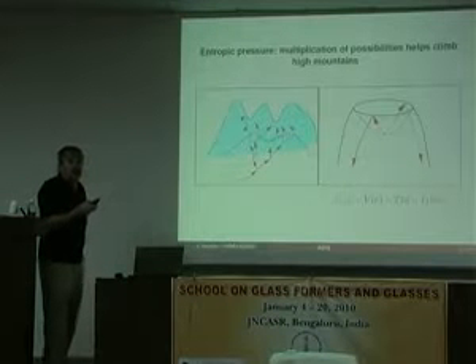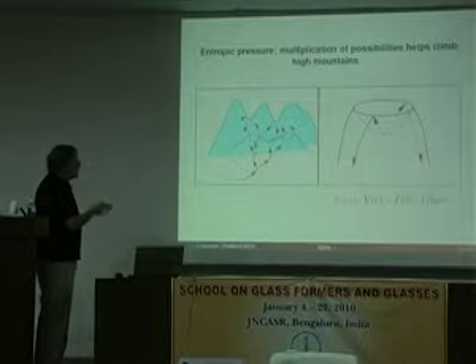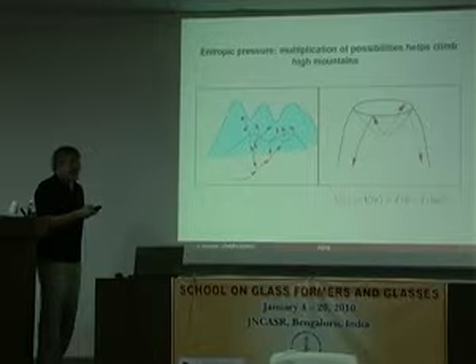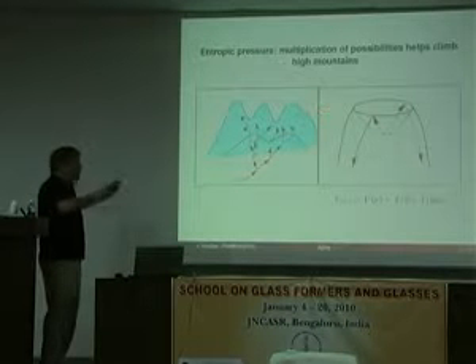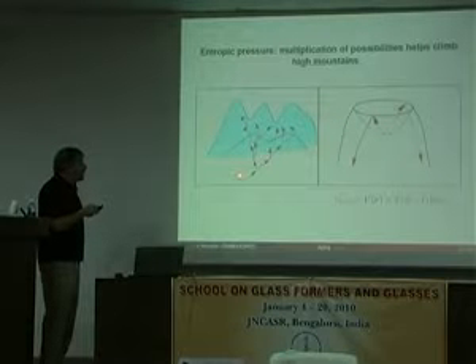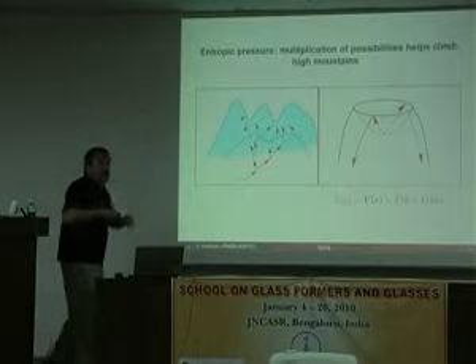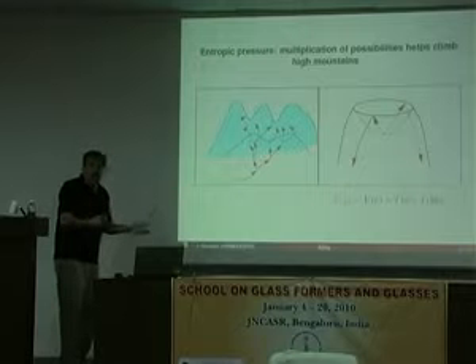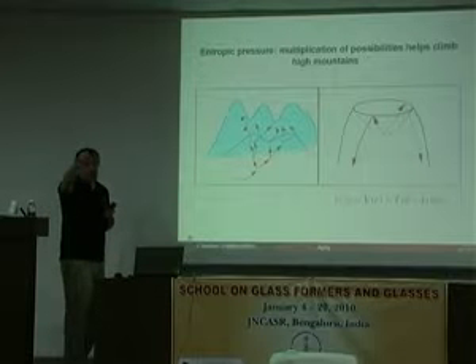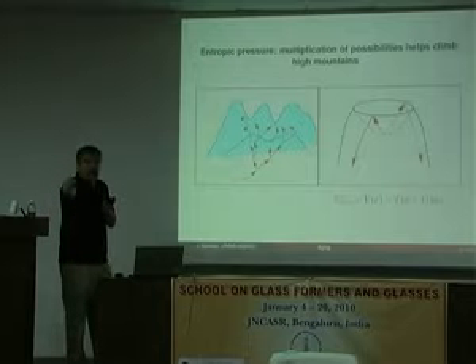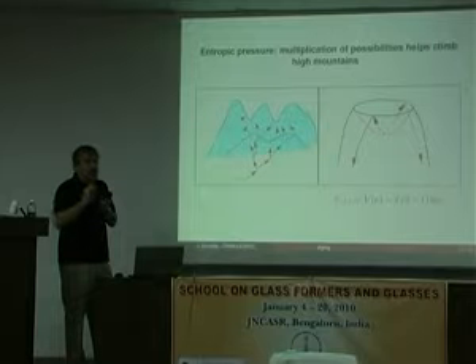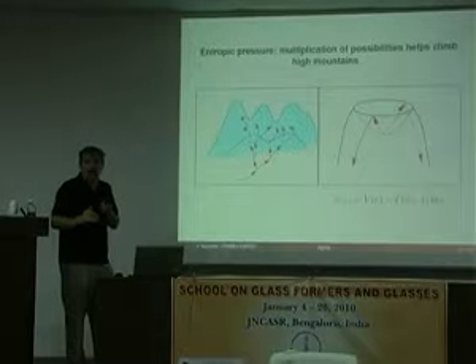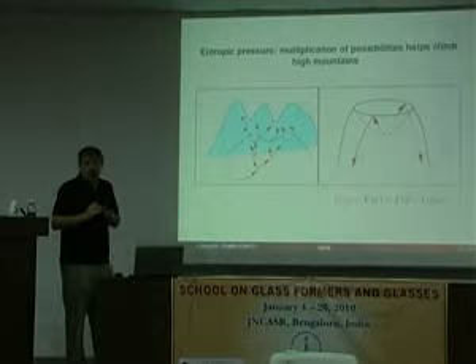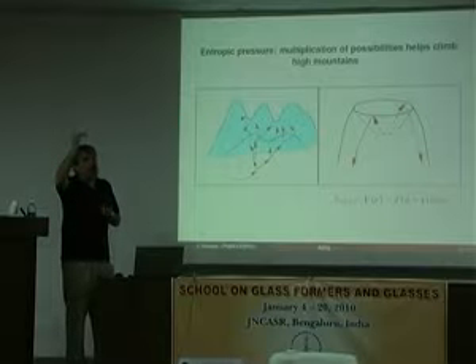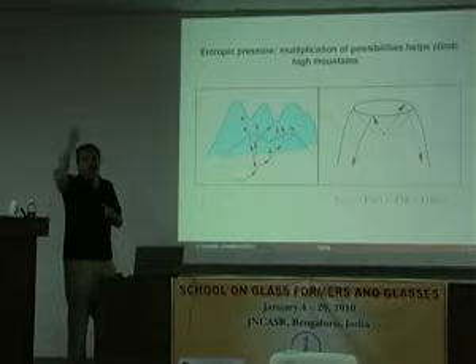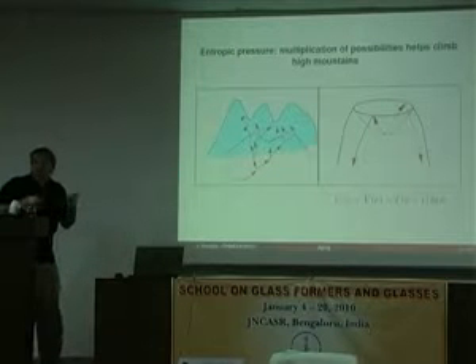There's another argument that is less known but more relevant to glasses, which you can calculate when you want to climb a mountain in phase space. And the mountain is very, very high, the Himalayas, but you have many, many paths. Then the time scale for crossing is depressed by the abundance of paths. Because you don't have to think of a path, an activated situation, as something that happens once in a while. What's going on is that you're trying all the time, and for every time you went to 90% of the barrier and failed, there will be many more times where you went to 80% of the barrier and failed, and many less times where you went to 99% of the barrier and failed, and only very once in a while you went 100% and couldn't make it to the other side.